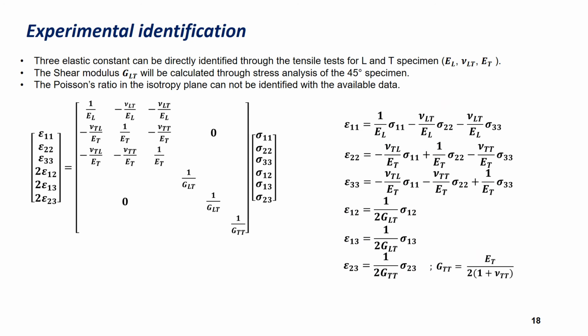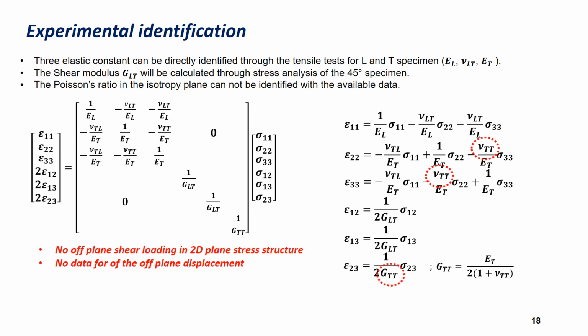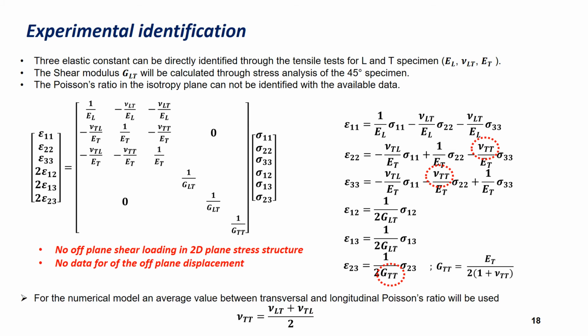For experimental identification, three elastic constants are directly identified through tensile tests: longitudinal and transverse Young modulus and in-plane Poisson ratio. The shear modulus will be calculated through stress analysis of the 45 degrees specimen. For the Poisson ratio in the isotropy plane, we are working with a plane stress geometry and only performing DIC on the surface. As the following equations show, this elastic constant is activated when we have off-plane shear loading or out-of-plane stress, and we need to measure the out-of-plane displacement. For our study, we will use an average value between both values for longitudinal and transversal specimens.